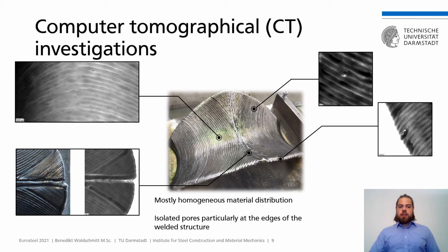A critical area is the center of the bridge where the two bridge sides meet, shown in the lower left image. To ensure the bond, an additional welding layer was applied in the transverse direction. Nevertheless, it can be seen on the CT scan that this was not done to the same extent in the lower half of the bridge as in the upper area. Another transverse seam could solve this problem. An additional seam applied on the underside would also be conceivable.